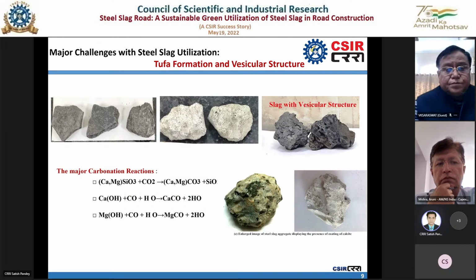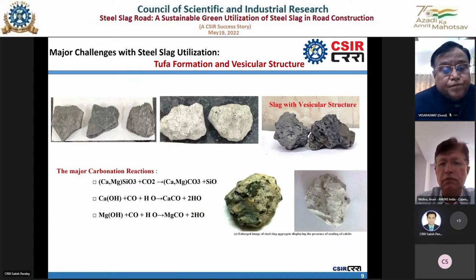And the third important aspect is the vesicular structure of the slag. Conventionally, steel slag looks like that, but with the help of the modified steel valorization technology developed under this particular study, this vesicular structured slag is successfully converted into an aggregate. So this is a glimpse of a processed steel slag aggregate, which looks like a good quality natural aggregate, so that it can be utilized without any issue in road construction work.